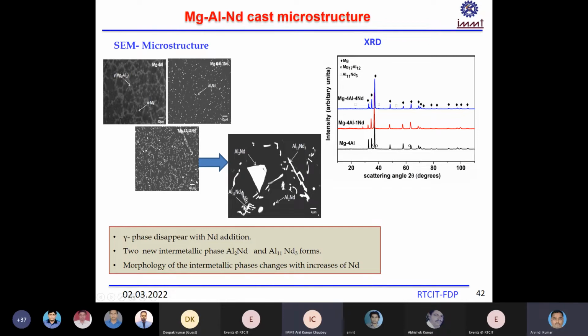So we went from 1 to 4%, and in 4% it was found to be very good. In between, we also studied the creep resistance. Creep resistance is increasing, but at 3 to 4% we have found better creep resistance. The data is not shown here, please. For creep resistance, around 3% to 4% we found better creep resistance because of more intermetallics and the branching of intermetallics, which makes this alloy high in thermal resistance and improves the thermal property. These intermetallics are stable at temperatures between 300 to 400 degrees. So that was the requirement.